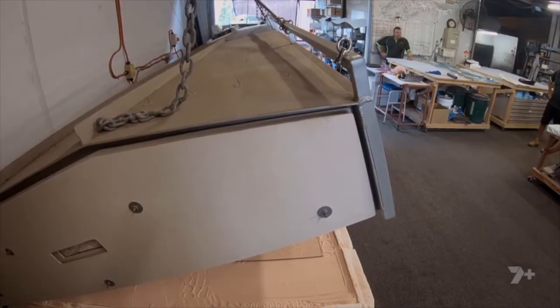Lisa then slowly heats the kiln to 800 degrees Celsius. This is now on for the next two to three days. And because the weather's so hot, it takes a bit longer to cool down. You've got to cool it naturally, because otherwise the glass will crack.